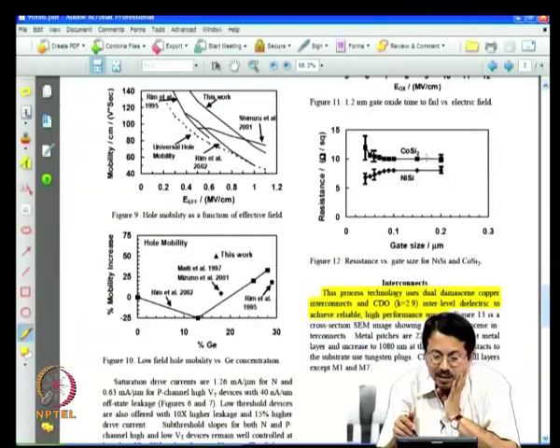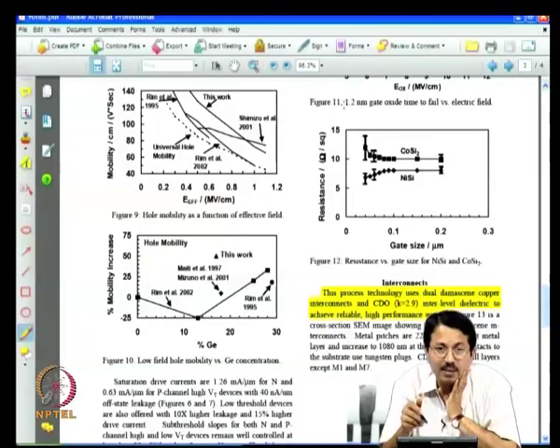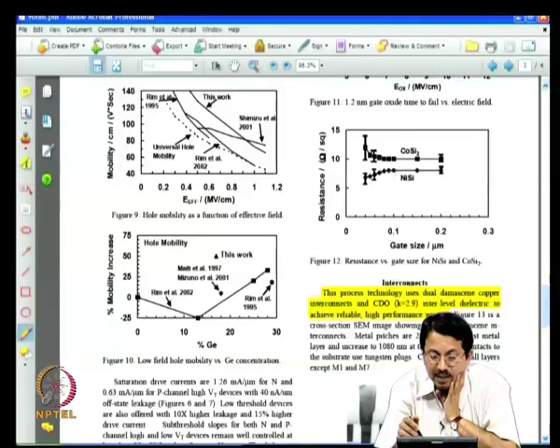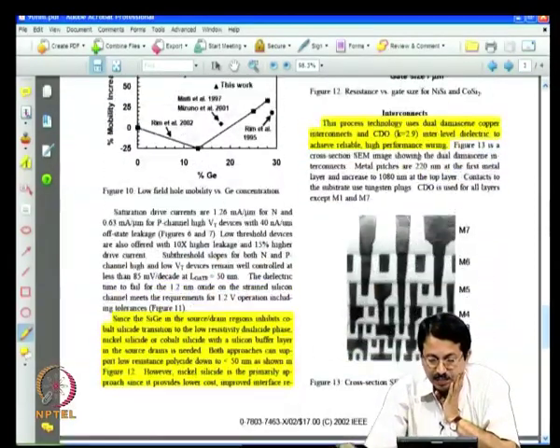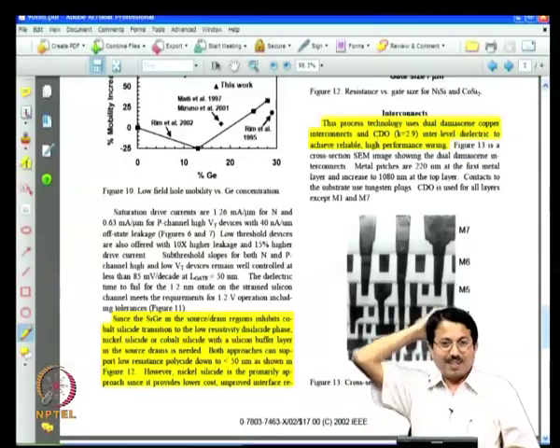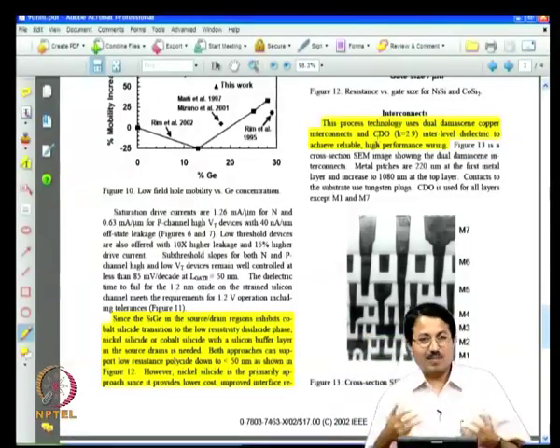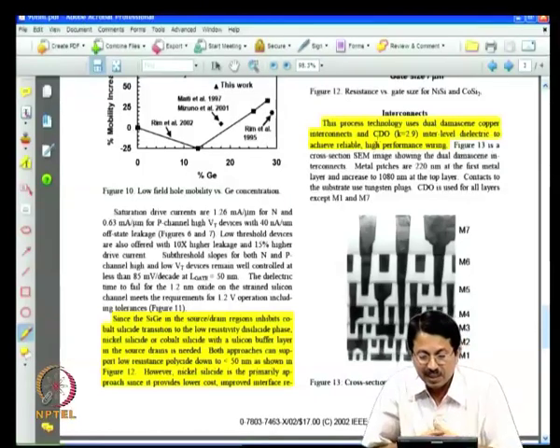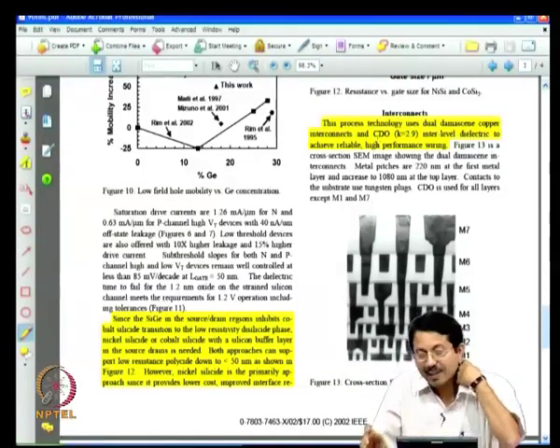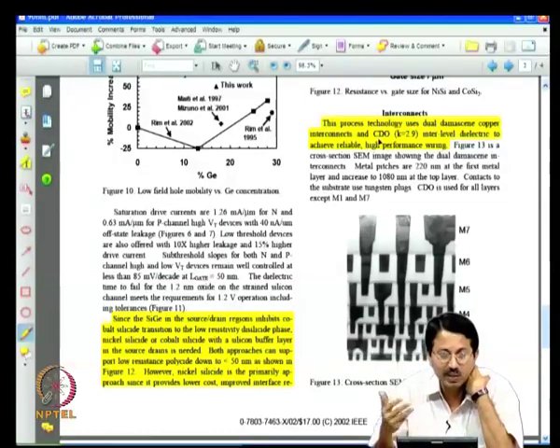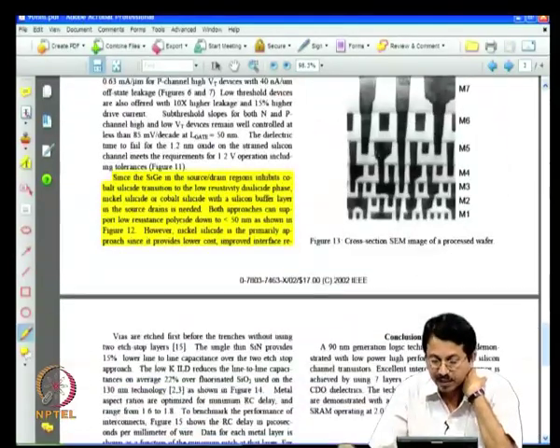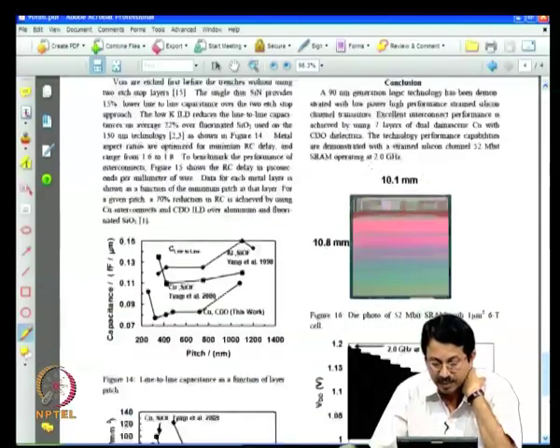Why nickel silicide? Because with scaling, cobalt silicide will start increasing the resistance, whereas nickel silicide gives very low resistance, and that is why they have gone to nickel silicide. Again, multi-level metal interconnects. Now, instead of fluorine doped oxide, they have used carbon doped oxide, again a new improvement. That is how you need newer and newer materials. K has come down to 2.9 instead of 3.5, again to decrease the RC delay of your metal interconnects.